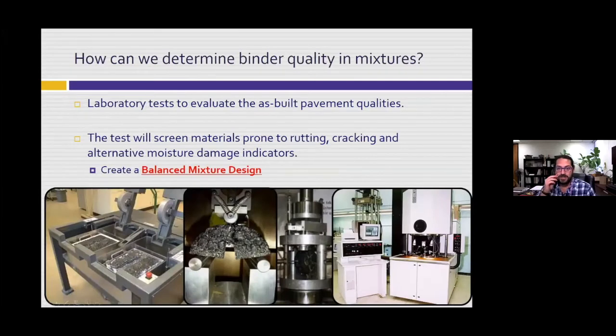And so how can we determine the quality of the binders that are being used in our mixtures? The most common way, and probably the most straightforward way, is to do laboratory testing to determine or characterize the properties of the materials going into the mixture, and then the mixture once everything's combined. And so initially what we were looking for is screening tests that would be able to screen out materials that would be prone to rutting, cracking, or moisture damage.